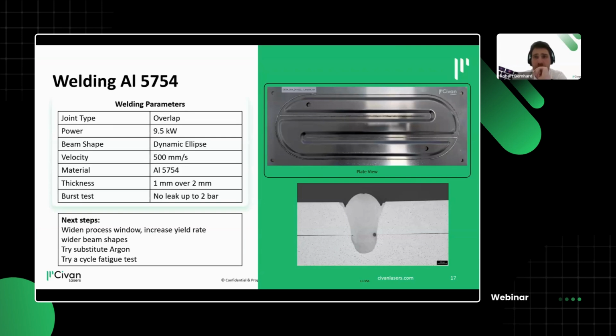And talking about this cooler specifically, we are using this demonstrator here because it's a non-NDA one. We can openly talk about it. So it's a dynamic ellipse, 500 millimeters per second. The top plate is 1 millimeter thick. The bottom plate is 2 millimeters thick. And we are able to achieve with this design leak tightness. We specified 2 bars, but I've seen the coolers bursting at 6 or 7. And then it's usually due to the design because we have inflation of this size.